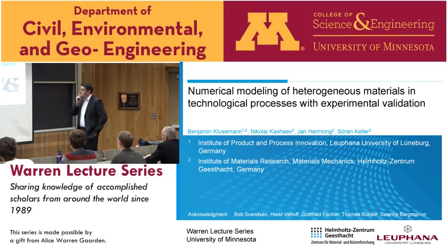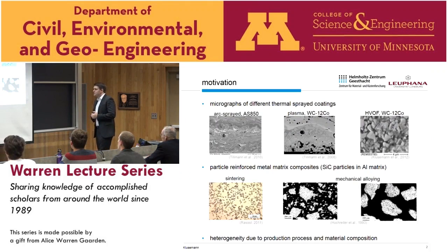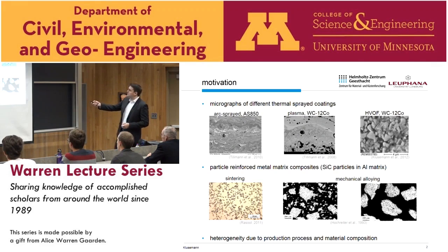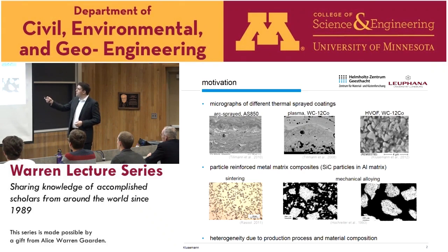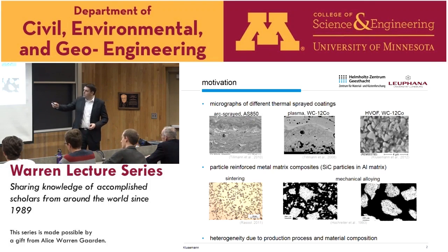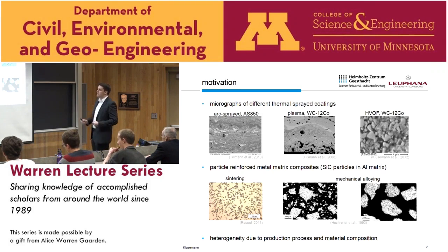So why are we actually interested in heterogeneous materials? Well, here are just some examples. So first of all, some micrographs, for example, of different thermal sprayed coatings. And you can see here, in particular, we have the same material composition. However, based on the process they are processed, one plasma spraying and one high velocity spraying, you see completely different microstructures. And of course, if you take a completely different composition, you have, of course, also some heterogeneity, which is very different to the other pictures.